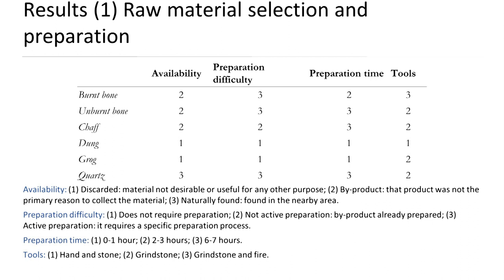By burning the bone, the process could be sped up considerably, although no clear evidence of burning this material for a temper has been observed in the LBK context. But we thought that it was an interesting aspect to investigate because most of the time it's not specified in the literature whether the bones added to the clay were previously burned or not. So that is an interesting aspect to keep in mind.